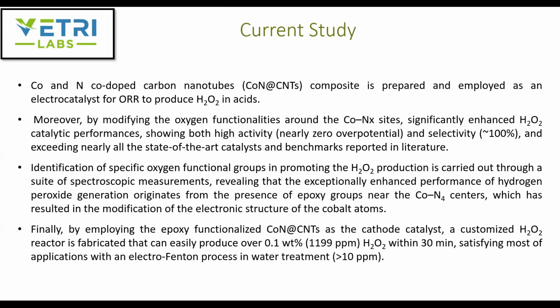This current study focuses on a cobalt and nitrogen co-doped carbon nanotubes composite, used for the oxygen reduction reaction, producing peroxide via a two electron transfer pathway. Moreover, they modified the oxygen functionalities around these metal nitrogen sites so that they could significantly enhance the catalytic performance, with almost zero overpotential and 100% selectivity towards peroxide. And the reported activity exceeds all the state-of-the-art and benchmark catalysts reported in the literature.